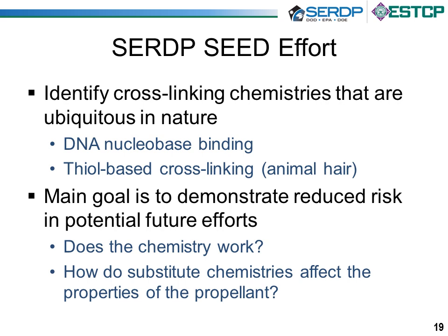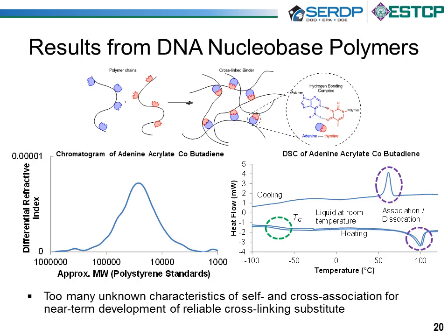So the results that you're seeing from DNA nucleobase binders on the screen, this is an example of something that was a great idea, and we were able to make a new kind of binding system for propellants out of it. But basically what we found is that there is an unexpected surprise in this material system. Because we are using a binding technology that involves polar molecules in a very nonpolar medium, which is unusual for these kind of systems. Normally they exist in a very polar medium. We find that there is basically self-association between the binders that we didn't expect.